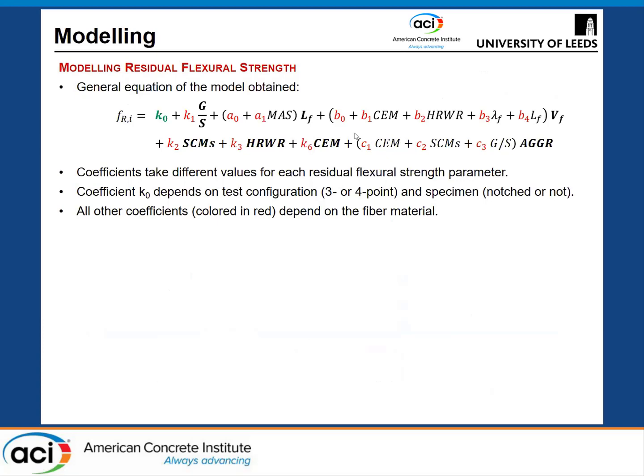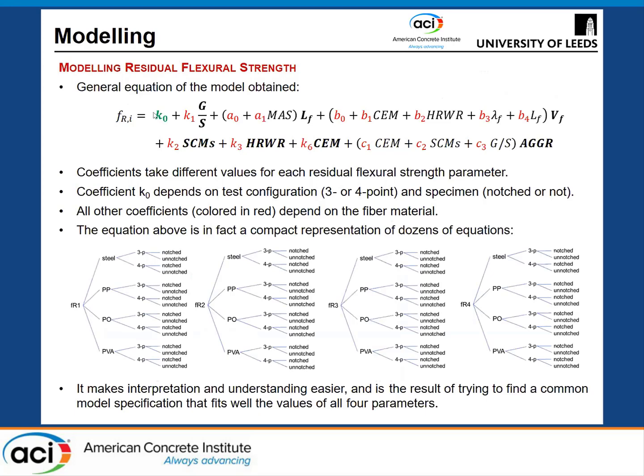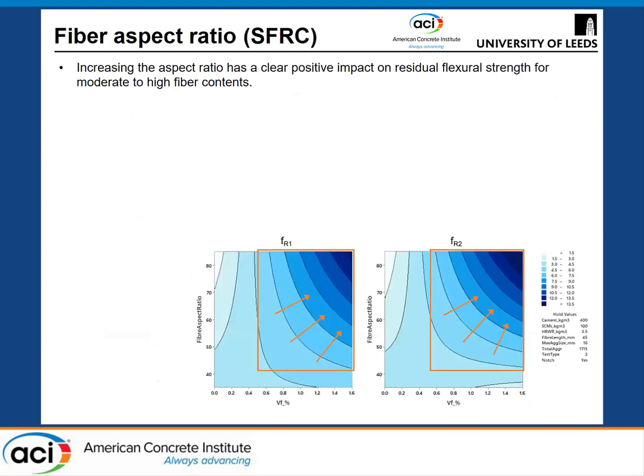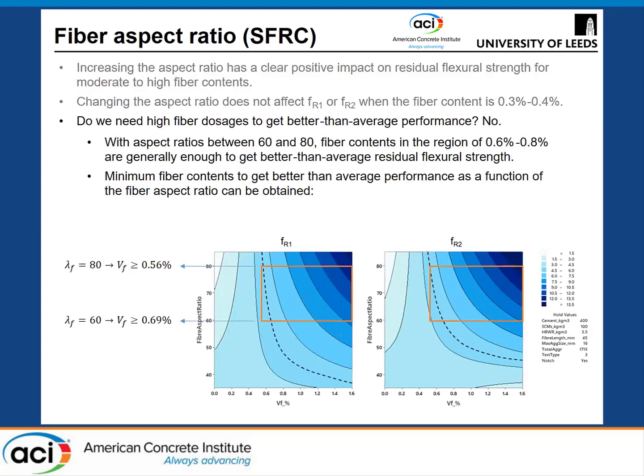But basically, we have 4 different residual flexural strength parameters. We obtained the same format of equation for the 4 of them. And it's simply a matter of that for each of the residual flexural strength parameters, the coefficients in red in this equation are different. So basically, in one equation, we were condensing dozens of equations for different cases. And all of them can be plotted automatically. So for example, here you can see for FR1 and FR2, the plots that show you the effect of volume fraction of fibers and the aspect ratio. So these are just a handful of plots that can be generated from using these models, and a few of the conclusions that I unfortunately don't have time to emphasize here.